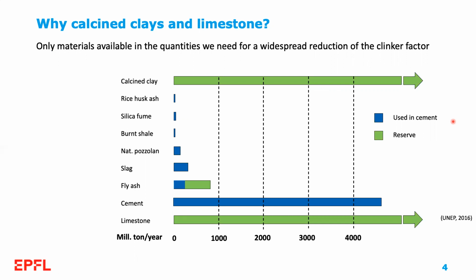Particularly here, I want to analyze the case of slag and fly ash, which are two materials that are widely used to blend cements. In the case of slag, the stock that we have worldwide is about 8% of the cement production, and it's actually decreasing as we recycle more steel rather than producing from iron ore. And in the case of fly ash, as we shut down our coal power plants, it's expected that this material will disappear by 2050.